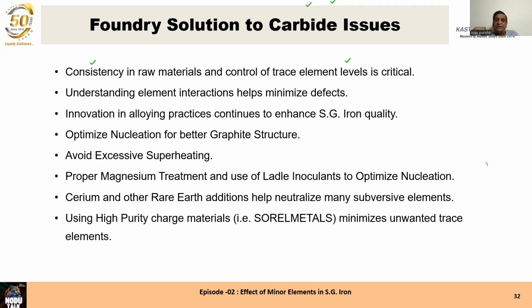Cerium and other rare earths additions help neutralize the bad effects of subversive elements, and using high purity charged materials such as Sorel metal, minimizes unwanted trace element buildup and effect of silicon. Please remember, we have got lot of problems with these subversive elements.